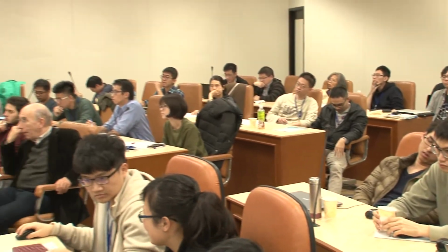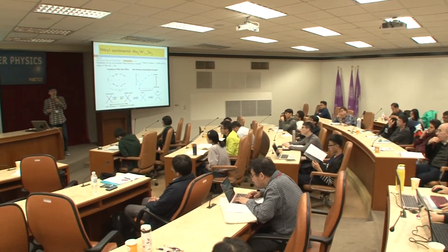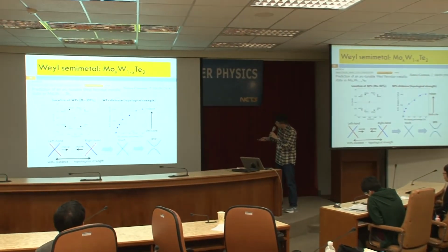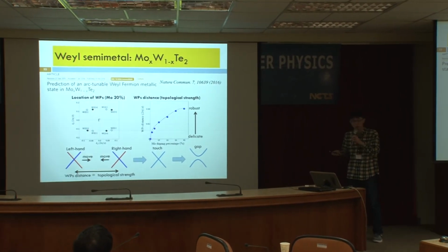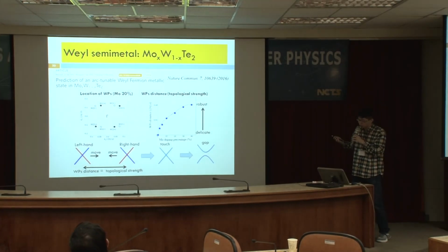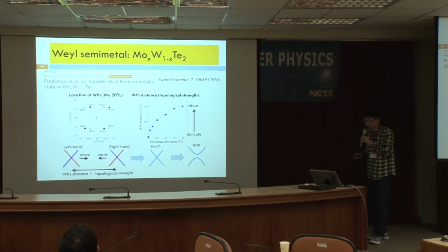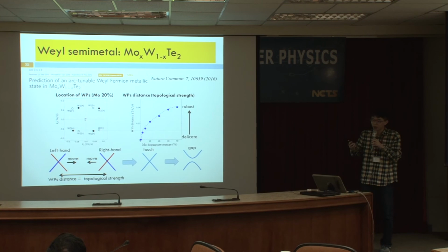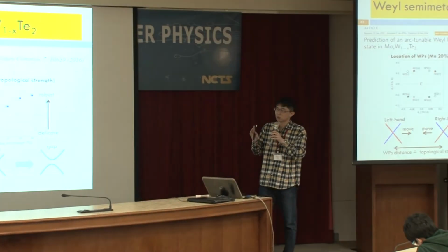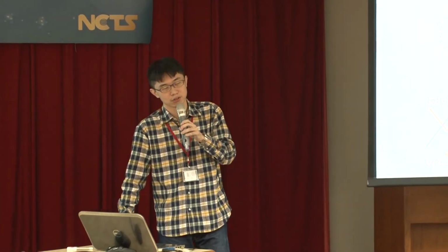As Professor Zhou mentioned, the supercell method may break the symmetry. So we only test some special values, for example 25% doping. It is consistent with our linear interpolation method, and we have used this method in other topological insulator systems. Again, fortunately, it is consistent with experimental data. So we guess that in 5d or 4d systems without strong correlation effects, maybe it's a good approach to study the doping system.